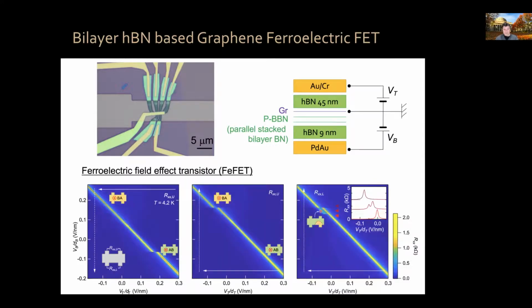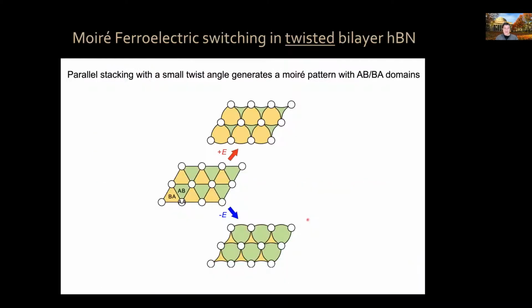Now, we can study this continuously as a function of bottom gate and top gate that we have in our structures. We can see the abrupt switching from BA to AB type of stacking. Then we can reverse and observe the opposite switching. Sometimes we can actually catch a domain wall boundary, a domain wall as it goes through our contact electrodes. So for a little while, there is actually this double peak in the resistivity, indicating the presence of 2 domains. Now, that is for perfect parallel stacking.